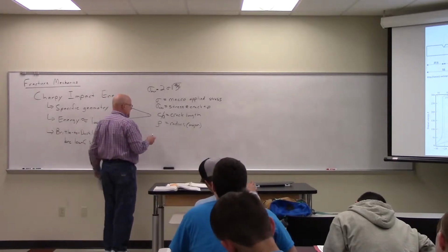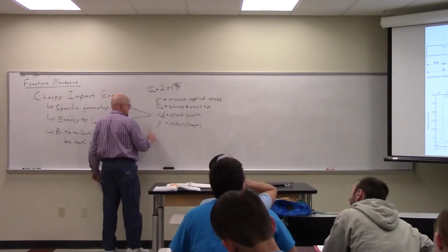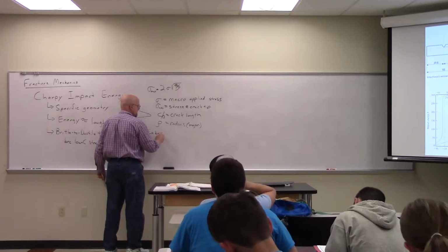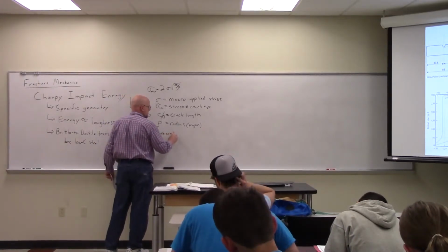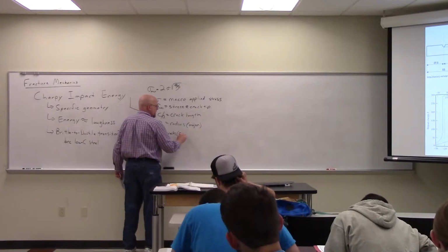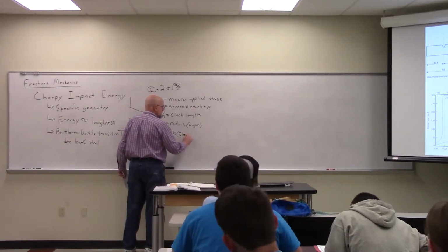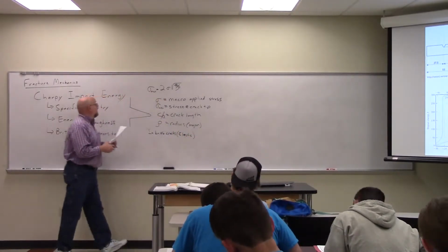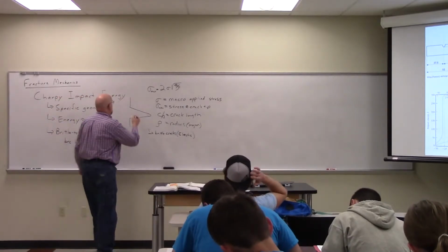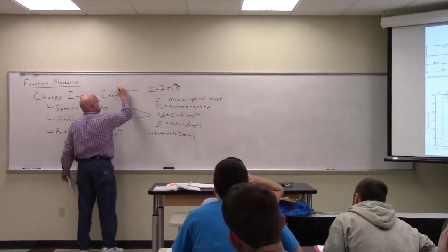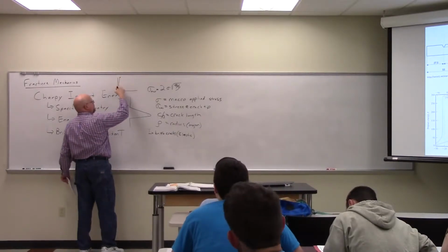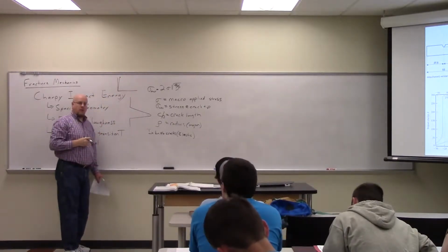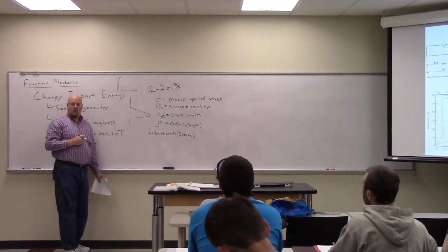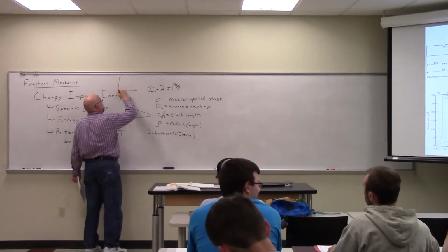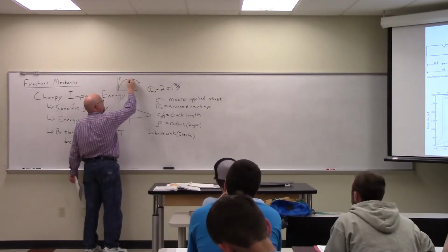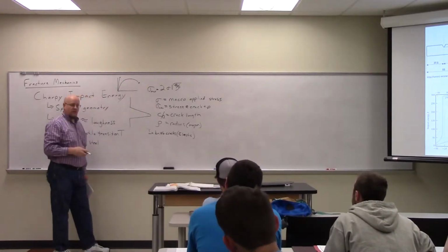It turns out that in brittle cracks, that is cracks where the material behaves elastically, right? Oh, I erased it. Nice. Draw it back up. So the brittle crack, we're essentially in the elastic regime. There's not really a lot of plasticity. Versus the ductile crack, which is going to have to operate where there's significant plasticity.